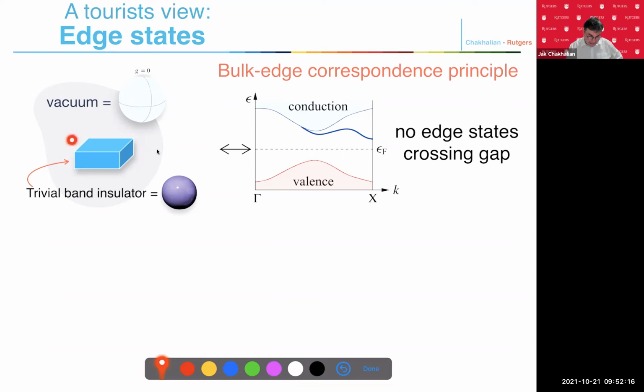So what will happen if I place my insulator into the vacuum? Well, very simple. Vacuum is equivalent to a sphere. So the vacuum is nothing particular. It's a sphere, and it has genus equal to 0. So no holes. But this structure, this trivial insulator, also has nothing interesting in there, and we can show very simply that any band insulator, in fact, is equivalent to a sphere as well. And so now we have inside a sphere, topologically a sphere, and in a vacuum, a sphere. And if I have a surface here, I'm going from genus equal to 0 to genus equal to 0, nothing happens. So placing a non-topological insulator into the vacuum does nothing. You will still get the same thing.